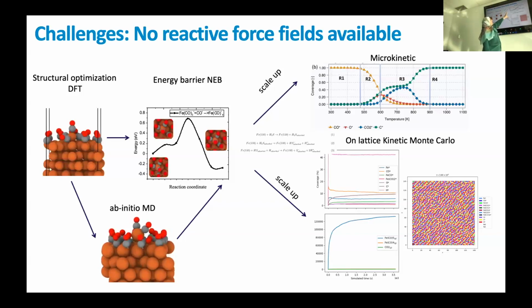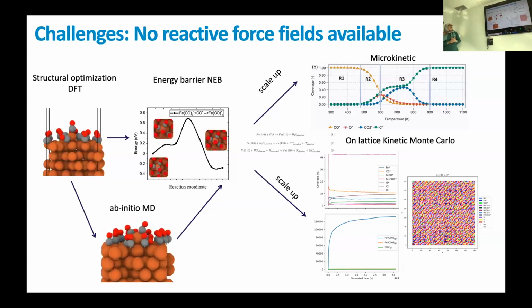In both cases, both of these methods, you start only from the equations for the reactions, to be able to look at the competition between the different species that are present in the system. So if you remember when I showed you the first slide, I told you about this competition between oxidation, reduction of CO and so on, each of these phenomena is at the origin of what is happening there. Okay? Here we went even further. But this is work which I cannot disclose yet. It's still under investigation by Shell scientists. So what we have done is that we also use our energetics to construct a finite element model to look at the pipe corrosion using a 1D diffusion model.